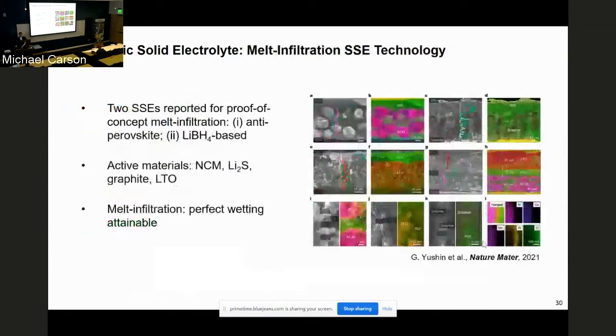And so we demonstrated this work on two exemplary electrolytes, anti-perovskite electrolyte and lithium borohydride-based electrolyte, but there are many others in development. And so we use both conventional materials such as lithium nickel cobalt manganese oxide, NCM material, again used in the majority of electric vehicles, but we also use conversion type materials such as lithium sulfide on the cathode, and then on the anode we use either graphite or LTO. And with melt infiltration, you can achieve perfect wetting, perfect contact between the particles. Again, very high density of the particle packing in electrodes, and very small fraction of inactive material or electrolyte.